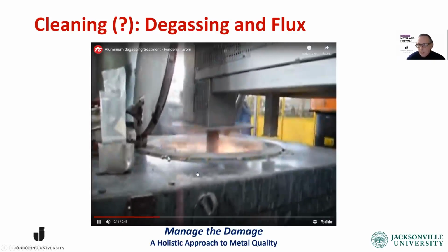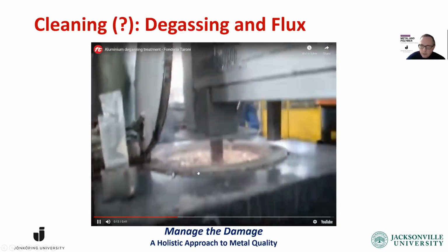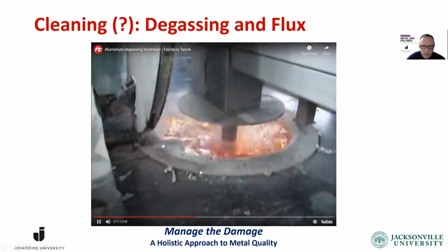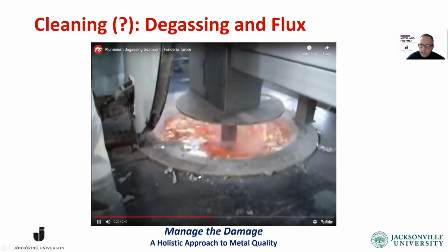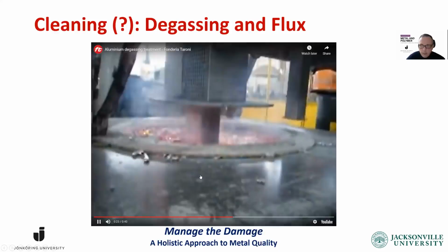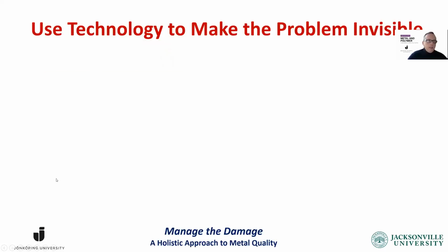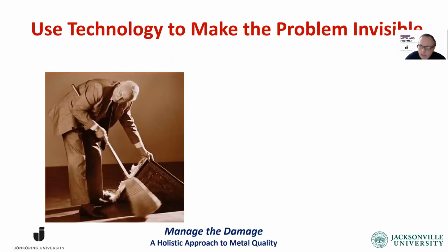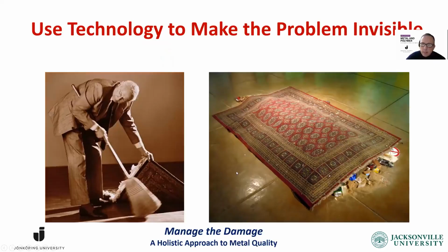But in the meantime, argon is pumped. Argon is known to take the hydrogen out of there, and we end up with metal with low hydrogen content, which is supposed to be clean. And we will talk about that later on. So what we do in this process is basically we use the broom technology. And what do we do with the broom? We take the dirt and we put it under the rug so we don't see it. If I don't see the dirt, if I don't see the damage, then it doesn't exist. And I wish life were that simple, because they come back to haunt us.